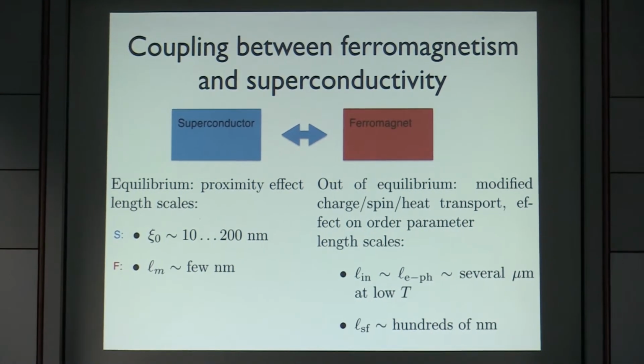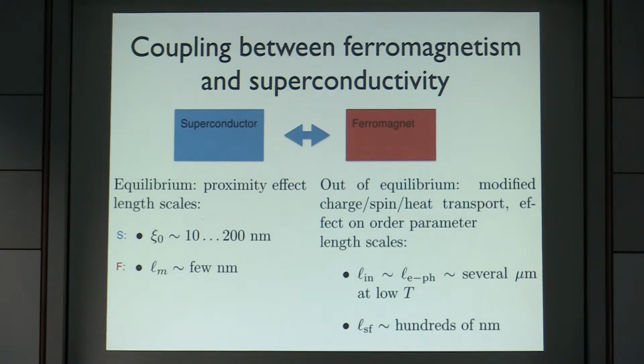Now, this is in contrast to out of equilibrium effects, which are related with, let's say, looking at what happens to charge, spin, heat transport, and then in this case, the relevant length scale is rather the relaxation length. For charge, the charge is usually conserved, so there might not even be a relaxation length. There is a relaxation length for charge imbalance. This is typically very long, but the other length scales are typically the inelastic scattering lengths, which at low temperatures below 1 Kelvin, where we are interested mostly because of superconductivity, are up to several micrometers. And then for spin effects, there is the spin flip relaxation length, which is typically hundreds of nanometers in metals.